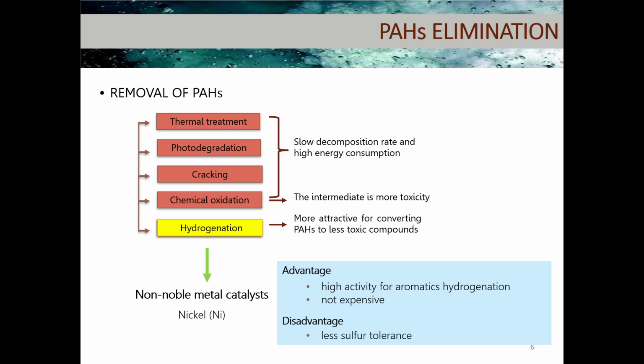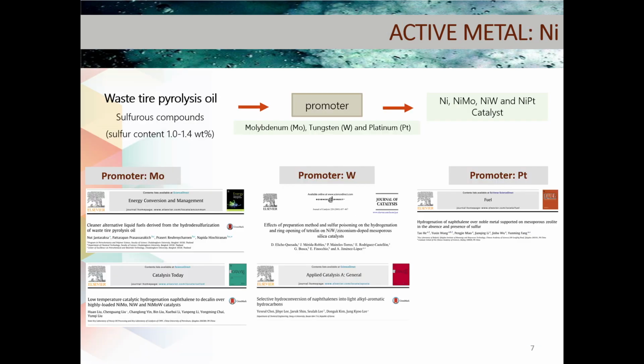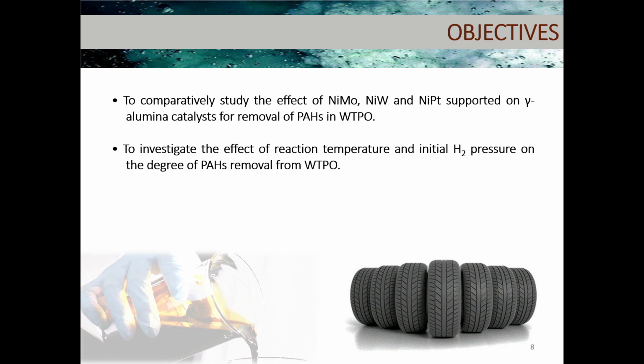So we need to seek a non-noble metal catalyst like nickel, because it also has high activity for aromatic hydrogenation and is not expensive. But the disadvantage of the nickel catalyst is that its sulfur tolerance is very low. So we need a suitable promoter to enhance the efficiency of the nickel catalyst. In this research, we selected molybdenum, tungsten, and platinum as promoters for the nickel catalyst, because the waste-tire pyrolysis oil contains a large amount of sulfur compounds. The objective of this research is to comparatively study the effect of nickel-molybdenum, nickel-tungsten, and nickel-platinum supported on gamma alumina catalysts to remove the PAH in the WTPO.